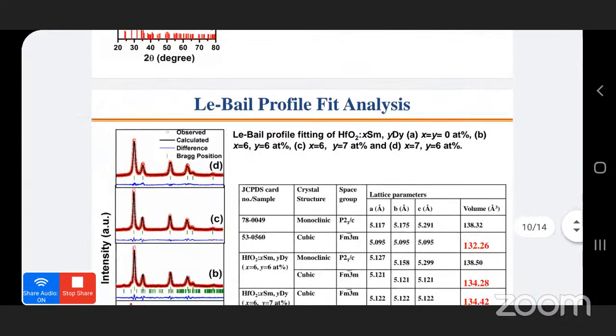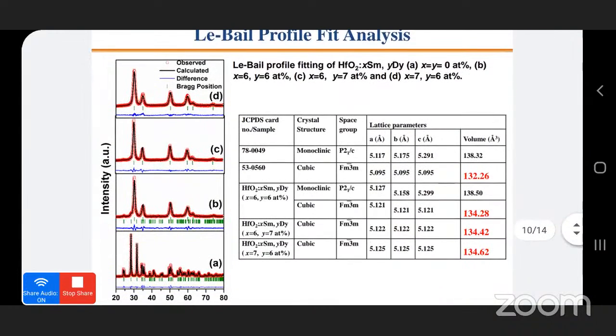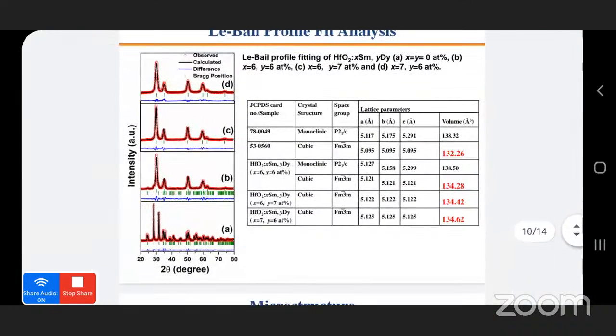Further, we did a Le Bail profile fit analysis of these XRD patterns, and we found that for the Dy and samarium doped system, there is an increase in the lattice volume of the cubic phase. For the cubic phase normally stabilized at room temperature, the lattice volume is about 132.26 angstrom cubed. But in this case, the lattice volume is very high, about 134.5 angstrom cubed.